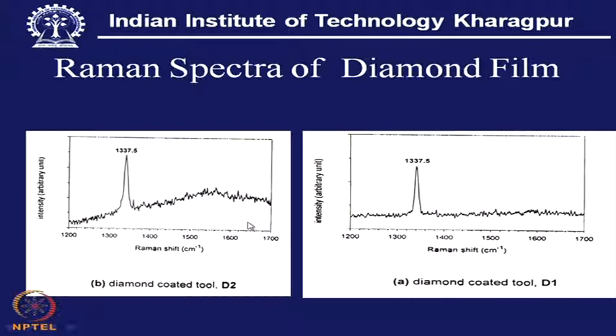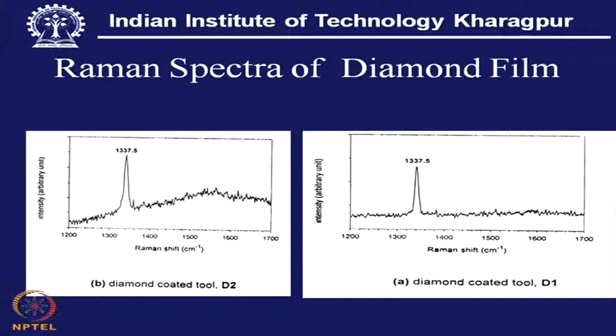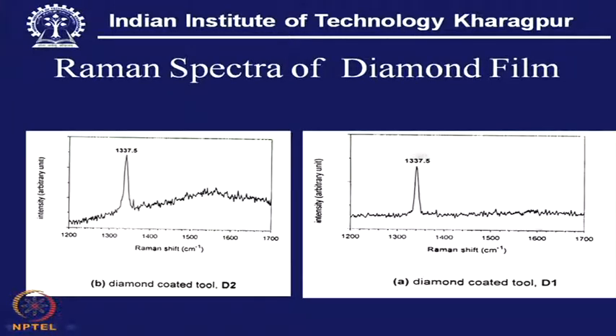So, accordingly, this is a very delicate process dealing with the CH4 to H2 flow ratio, the process pressure, and the substrate temperature, but finally the outcome is here, and this is this Raman spectroscopy. From that we get to know the quality of the coating. It is not just AFM or the X-ray diffraction diagram, but this Raman shift from the Raman spectrum that tells us the quality of the coating. So, all effort should be made to have a spectrum like this, or even better, with no hump formation, and that will give us a clear idea about the quality of the coating.